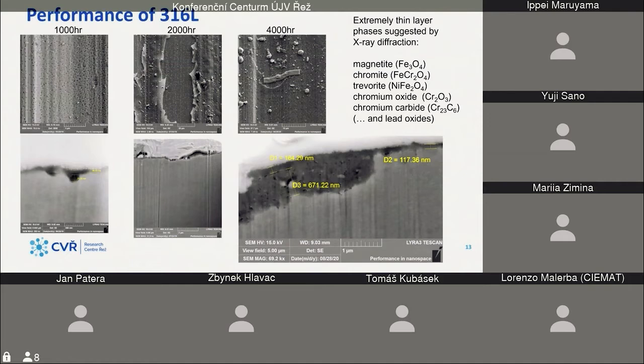Over time, the evolution is that stainless steel forms a few hundred nanometers thin layer that after 2000 to 4000 hours starts peeling off. It's challenging for analysis because it's extremely thin. So we use some X-ray diffraction, and the preliminary results show that there is obviously magnetite, some chromium oxides, but also, surprisingly, nickel. Nickel oxide is involved. It's quite interesting since the oxygen level is lower than what is needed for stable nickel oxide. But in this spinel, it's not a problem, so it's quite a nice result.